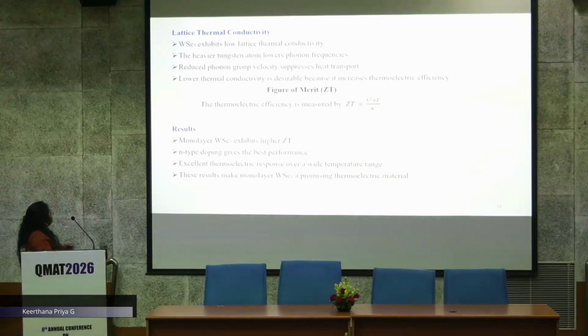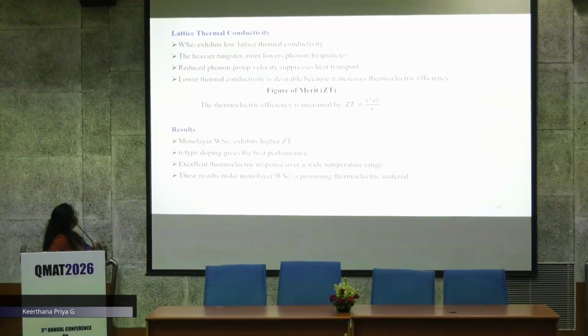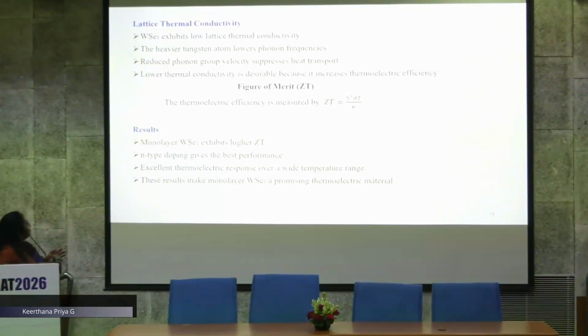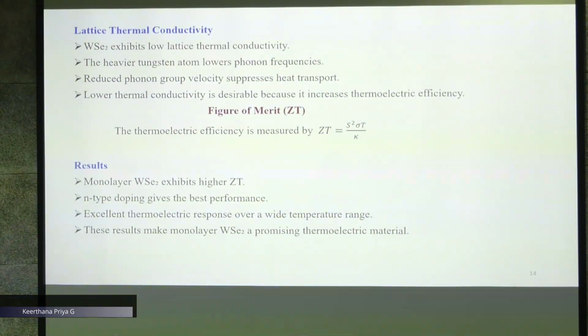Moving on to the lattice thermal conductivity, here WSe2 exhibits low lattice thermal conductivity, and the heavier tungsten atom lowers the phonon frequency. This also reduces the group velocity, suppressing heat transport, and the low thermal conductivity is desirable because it increases the thermoelectric efficiency.